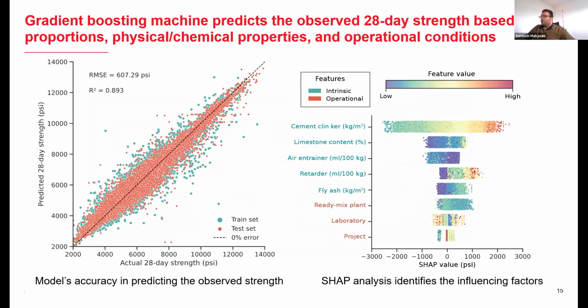So by using the SHAP model, we could identify the influencing factors. On the left-hand side, this is the goodness of fit for the machine learning model, a gradient boosting machine, that predicts the observed 28-day strength based on the mix proportions, physical and chemical properties, and operational conditions. We considered the ready-mix plant, laboratory, and projects here as input variables for this model, and there are over 30 different input features here, and I've shown you only 5 of them on the right-hand side, the ones that have the highest influence on the predictions. So we found that cement clinker, for example, has the highest impact on the compressive strength, and limestone content, etc. So these are the intrinsic features that we have considered.